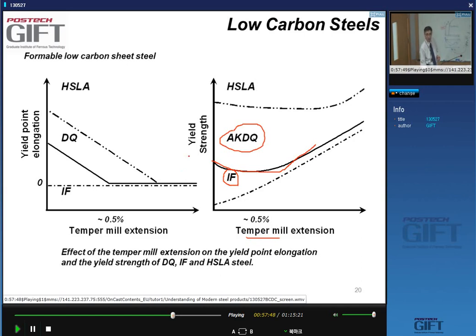An IF steel, titanium IF steel, always has a continuous stress-strain curve, with no yield point elongation. So if you temper roll the material, the only thing that happens is you increase the yield strength, right? So you have a very different response to temper rolling.